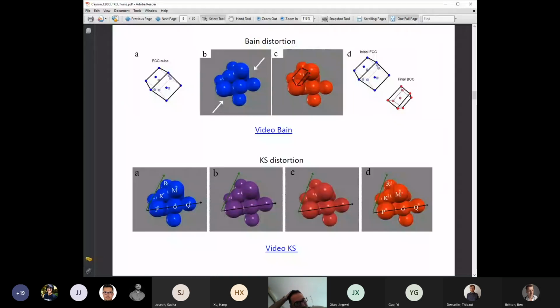You can do that for FCC to BCC. You can do the same calculation. Okay, it can be complex, but in principle, it's not difficult to understand. So you can make a movie of what is a Bain distortion, or the same distortion composed with the rotation, which gives you the final Kurdyumov-Sachs orientation relationship if you need. So you can do a lot of calculation.